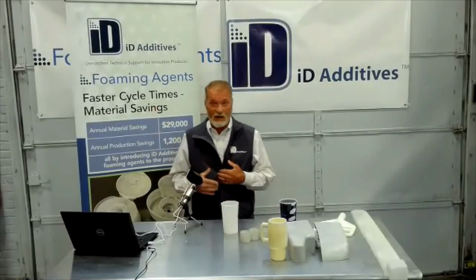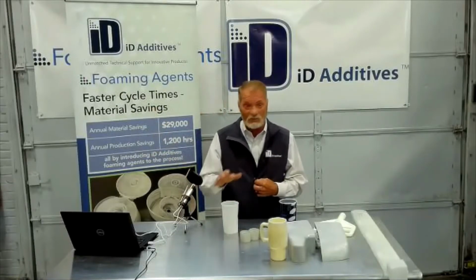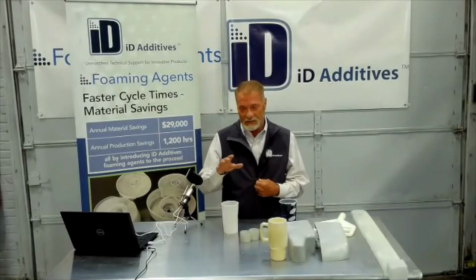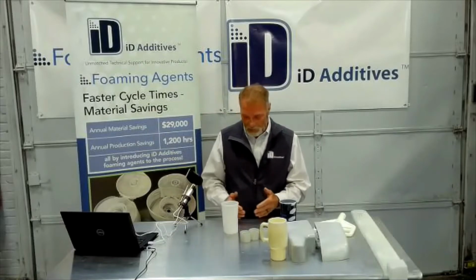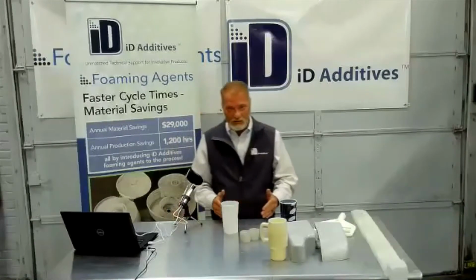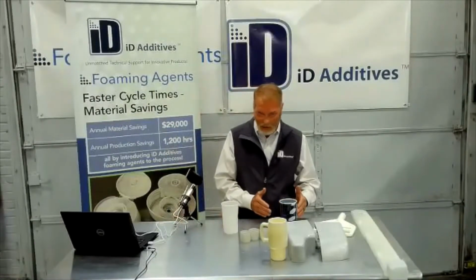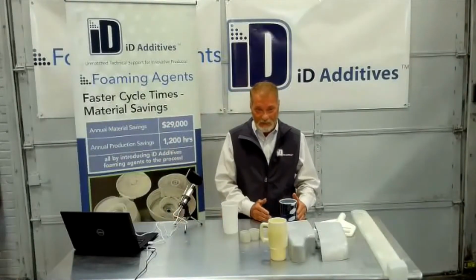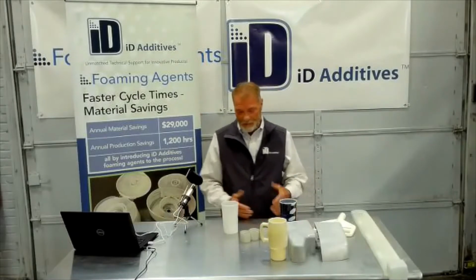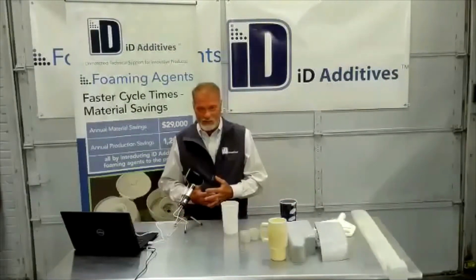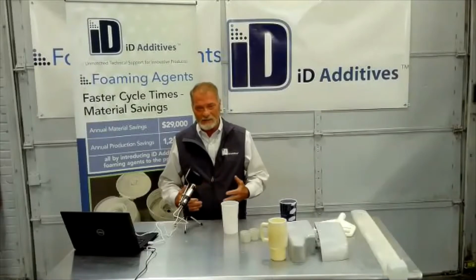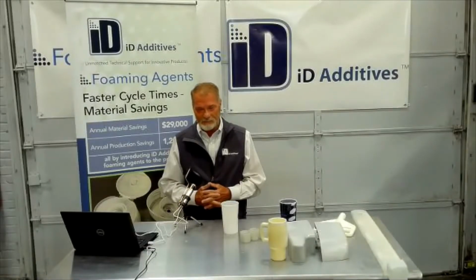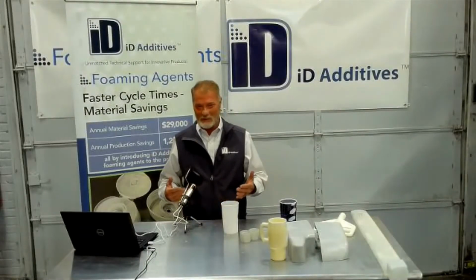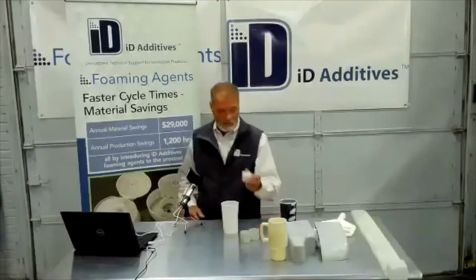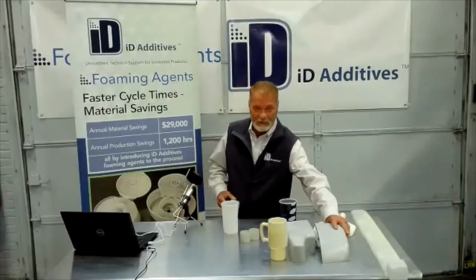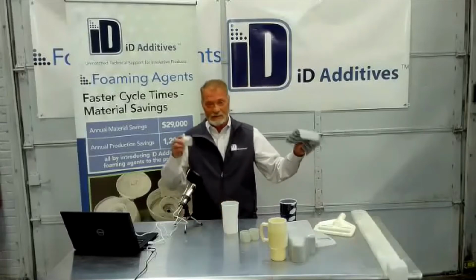We want to make sure everyone gets the most out of it, and that it's done to where you control the bubble with temperatures, with injection velocity, and again, it's low pressure. Let the foam do the work. And thicker parts tend to be a little easier to do aesthetically, only because it's a thicker part. You don't have to inject it in as fast as you would something like this, as opposed to a thick part like that. Big difference.